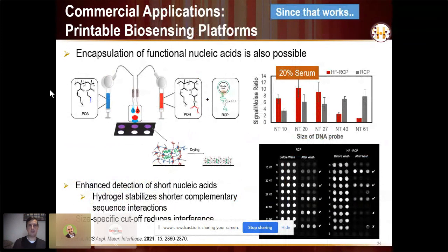We've also tried to expand this to see, well, if we can encapsulate enzymes, can we encapsulate other things? And this is an example of a rolling circle amplification, or RCA, product, which is just a really long strand of repeated DNA sequences, up to a megadalton molecular weight of the same DNA sequence over and over and over again. What we saw when we print this in our hydrogel using the exact same printing strategy is that if the probe that we're trying to detect has a lot of base pairs, we no longer can detect it. So there's a selectivity based on the porosity of the gel, where these larger base pairs, which can be competing species, can't actually get in.